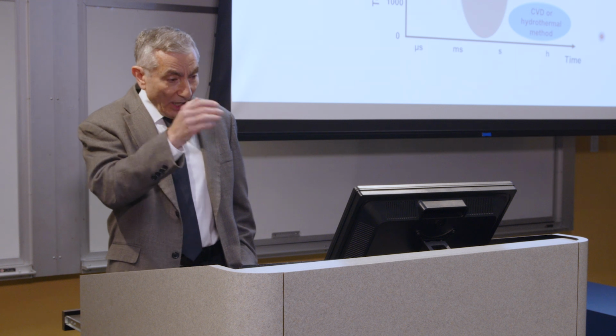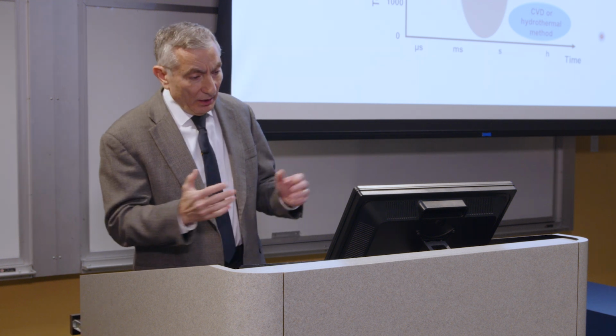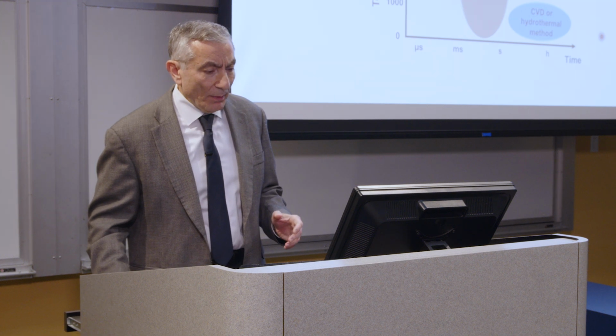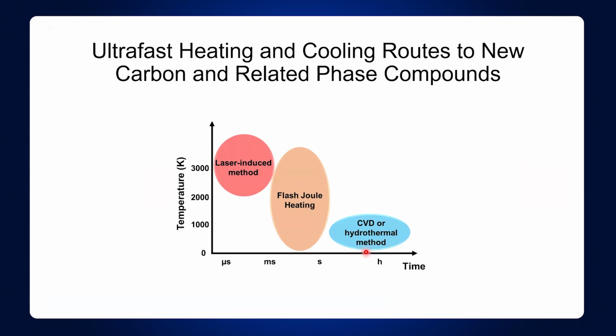So what we've gone through between last time and this time, and the other times, is a few different methods. Remember when we were growing graphene, you'd put this in a furnace and you'd feed in a gas and it would grow on a surface. The graphene would grow on copper, say. That took anywhere from minutes to hours to do. That was called CVD. Then we looked at laser-induced graphene. Remember, that was a laser method. That's forming in microseconds. And what we've just done is we talked about flash joule heating. That's forming from milliseconds to seconds. That's the time frame. And so these are three different methods to do synthesis of these nanoscale materials, and how to do these reactions at different time scales.